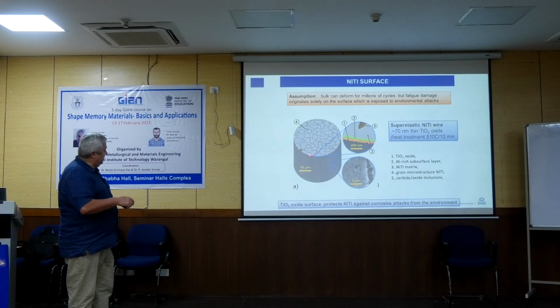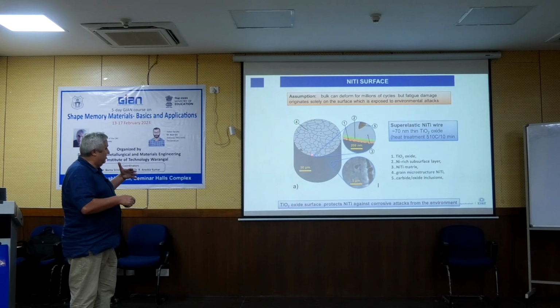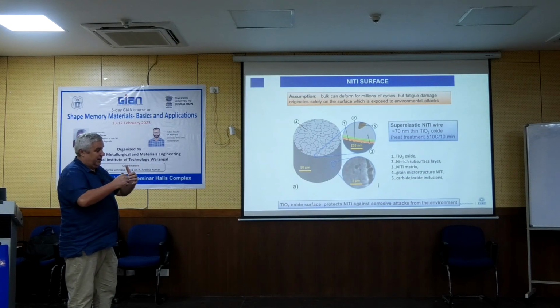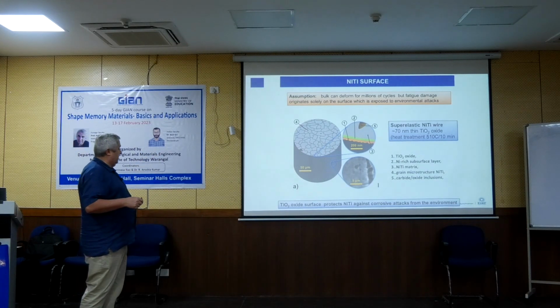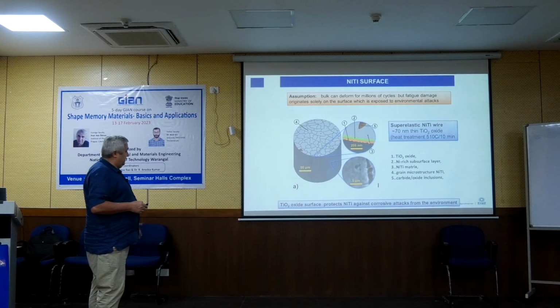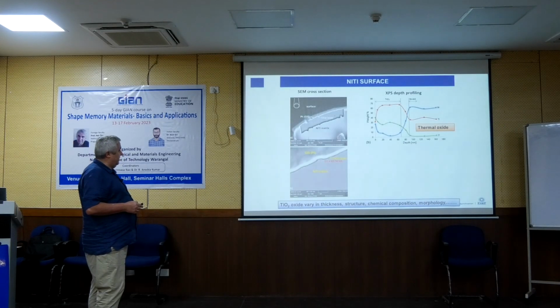And one additional problem, sometimes you have these carbides on the surface, and then there could be a source of a hole, a cavity, and this cavity, when you do the cyclic test, frequently becomes the center of main damage, which finally grows to the major crack. So I already spoke about that. But now we can get rid of the carbides, so the problem is with the oxide layer itself.